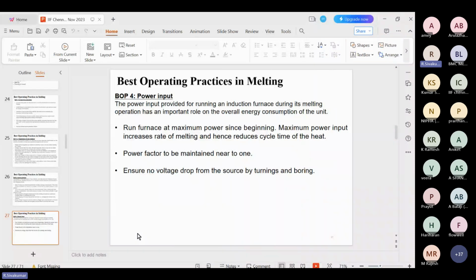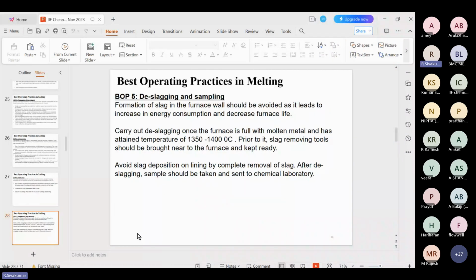Turnings and borings. Deslagging and sampling. Formation of slag in the furnace should be avoided, as it leads to an increase in energy consumption. Every slag adds some additional energy. So carry out the deslagging once the furnace is full with the molten metal and has attained the temperature of 1400 degrees. Avoid slag deposition and build-up by complete removal of slag.